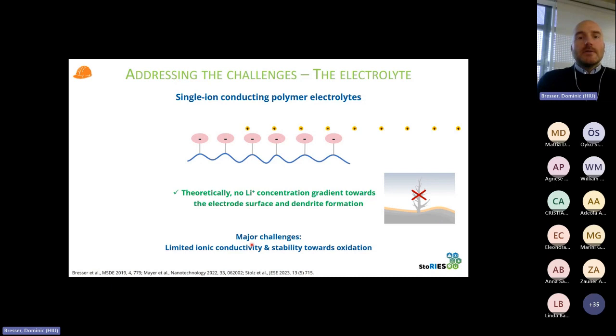But there are two major challenges related to these systems, which are limited ionic conductivity, because, as you basically mentioned, it's less mobile than when the anionic species is contributing as well. And we have a limited stability towards oxidation. This is not an issue only for single-ion conducting polymer electrolytes, but for polymer electrolytes in general. So also the PEO mentioned earlier still is basically limited to the combination with lithium iron phosphate, because the threshold is more or less 4 volts. So above 4 volts, it's oxidized. So LFP, lithium iron phosphate, with about 3.6 volts is kind of safe.